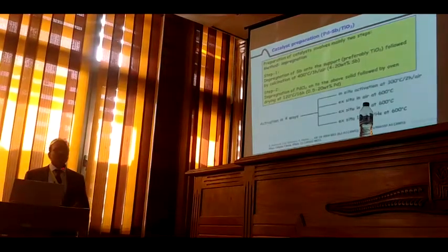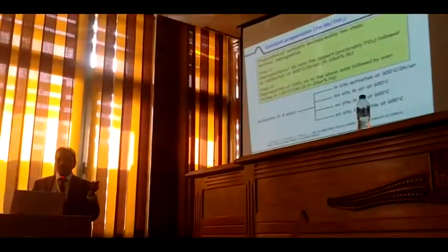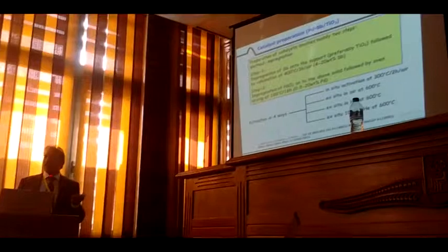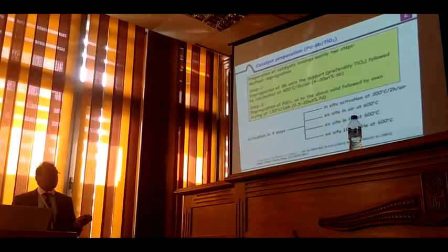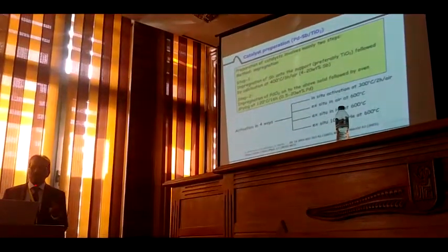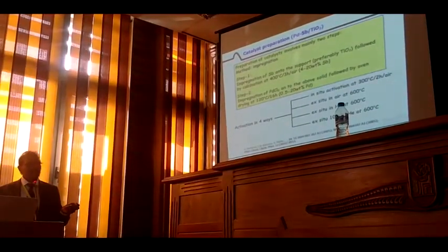And after impregnation, we know that palladium particle and palladium particle composition matters a lot for this reaction. We need bigger particles. In order to have bigger particles in the beginning itself, we gave different thermal treatments, with calcination treatments. First we calcine at 300 degrees centigrade in air. There was no formation of bigger particles. Then we thought, okay, we will calcine at high temperatures, 600 degrees in air, oxidizing, and then we want to see inert, and we want to see reducing atmosphere at 600 degrees centigrade, and see how the particle morphology and particle composition, particle size, shape changes with this thermal treatment. And every one has clear influence. We will see it later.